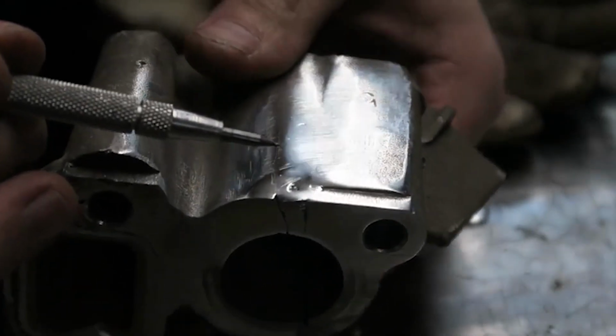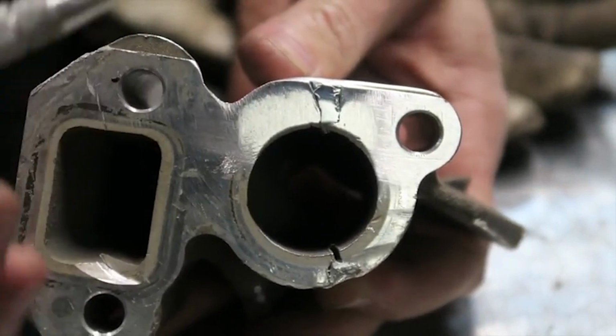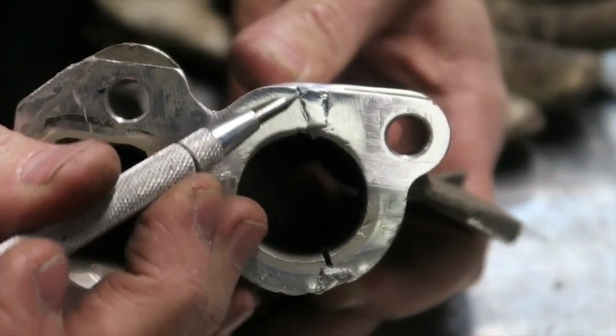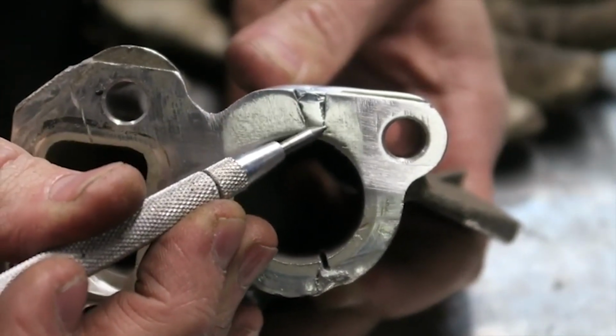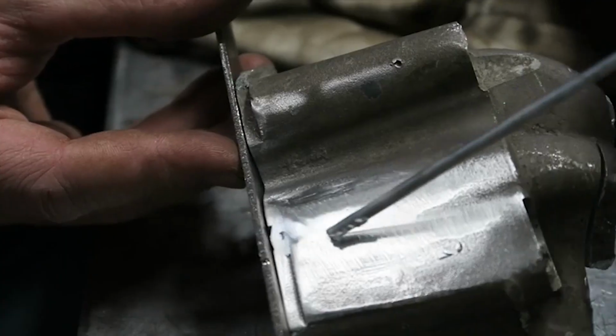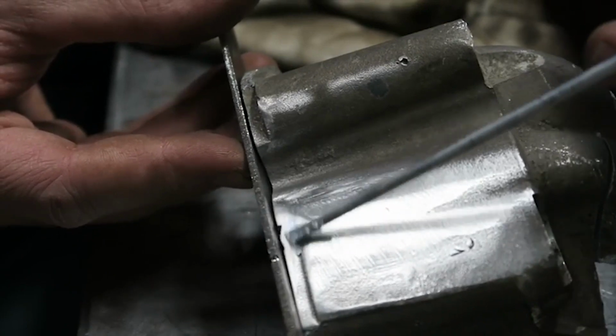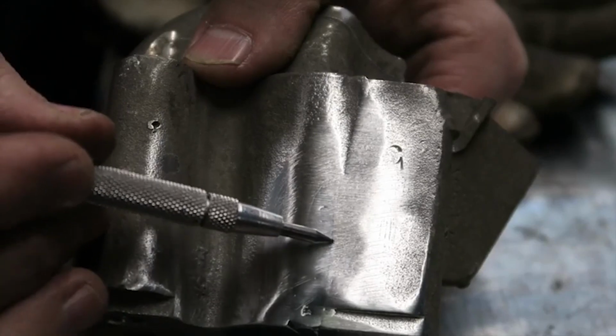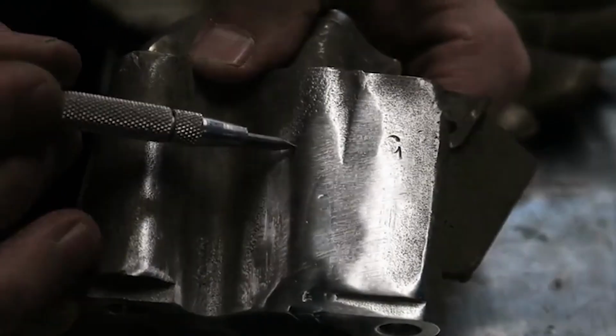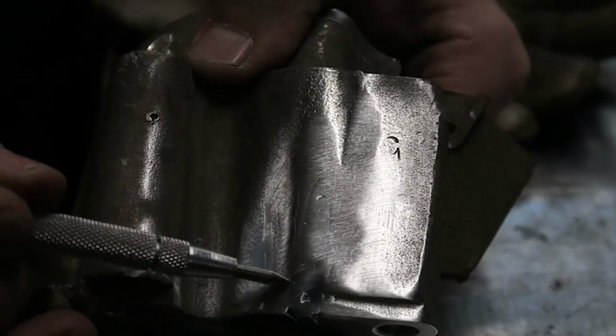As you can see on my repair, I failed to tin the mild steel dam I had put in place. Therefore, it did not flow all the way to that particular part of the mold. Had I been a little more careful with my application and worked it further down toward the dam itself, I would have gotten better results. But as you can see, the repair is barely noticeable. It is harder than the surrounding metal, and it is ready for service.